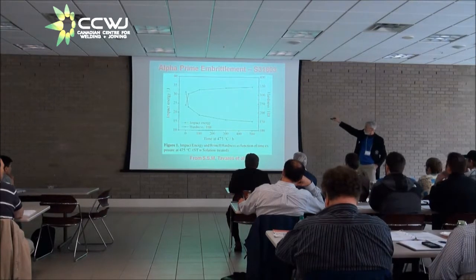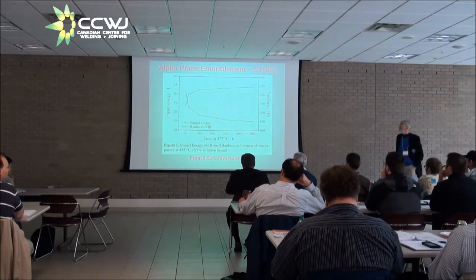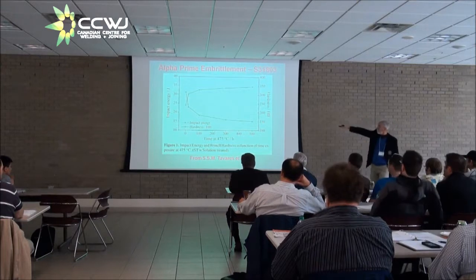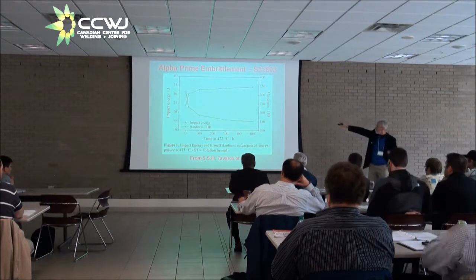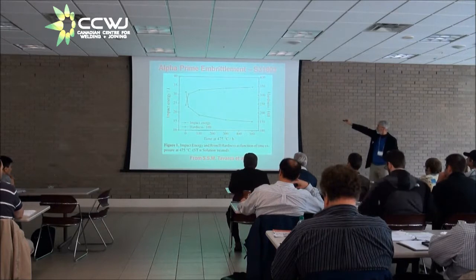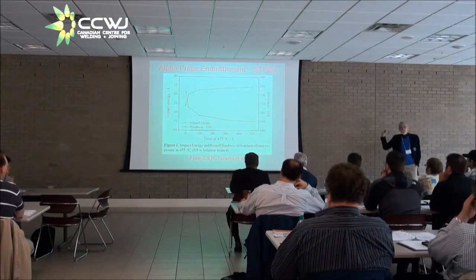So what you see in the impact results, Charpys start out at a bit over 30 joules and they drop in something on the order of 100 hours to less than half. And if you also look at the hardness of the material, he's using Brinell hardness. So the hardness starts at a number in the 220 area and it goes up with increasing time and temperature, so that you're up in the area of 350 Brinell after 500 hours. So there's a serious hardening of the alloy and a serious embrittlement of the alloy.